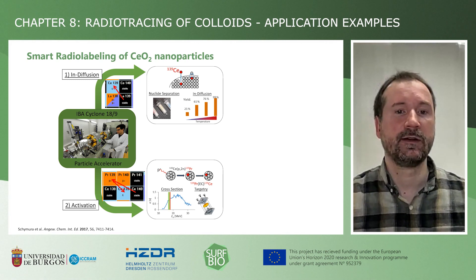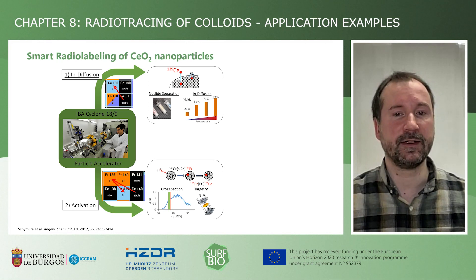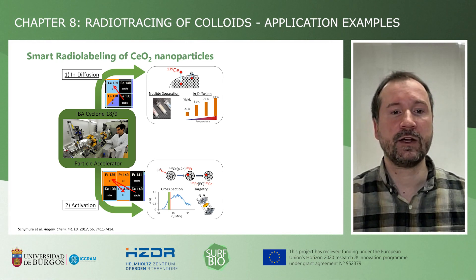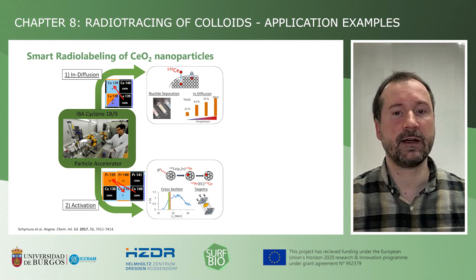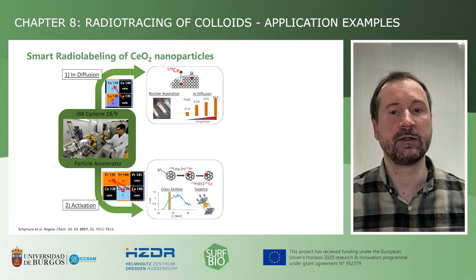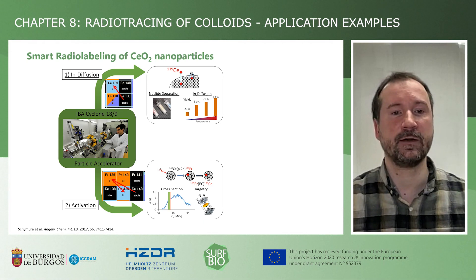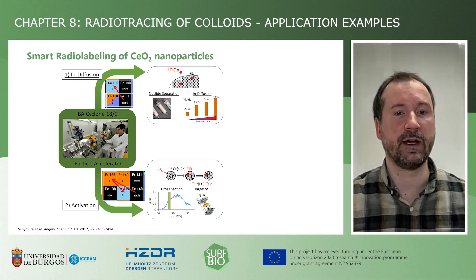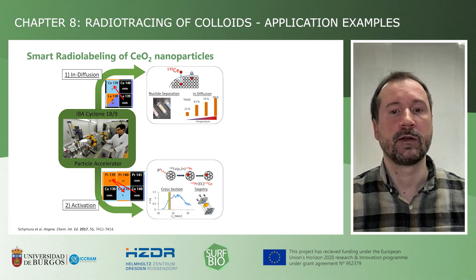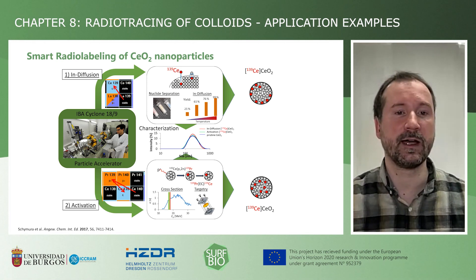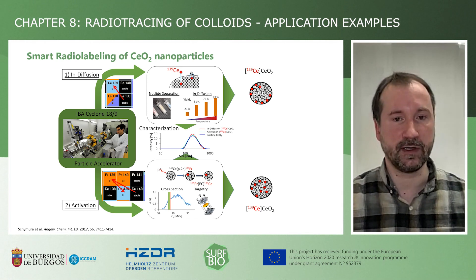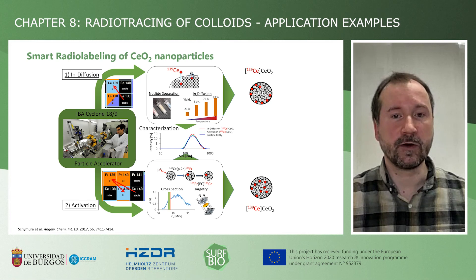The second method is the direct activation of the ceria nanopowder. Proton irradiation of ceria nanoparticles using a suitable target design at our cyclotron triggers the (p,2n) reaction from Cerium-140 to Praseodymium-139, which decays with a half-life of four hours to Cerium-139. So both methods produce Cerium-139 radiolabeled nanoparticles that physico-chemically are for all intents and purposes the same.